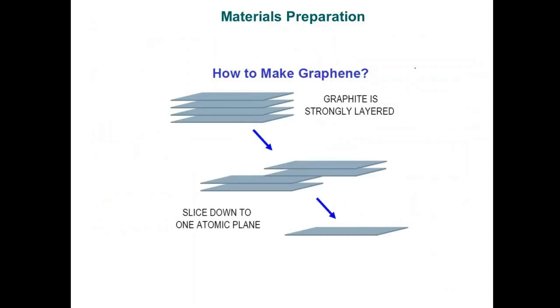How do we make graphene? Graphene can be prepared in many ways, but the graphene reported in literature is actually an exfoliated form of graphite. If you take a scotch tape and stick it onto graphite then peel it off, you notice that some material adheres to the scotch tape surface while keeping the substrate intact. If you do this n number of times, it may be possible to obtain a one-layer sheet of graphene. This method is basically an exfoliation method.